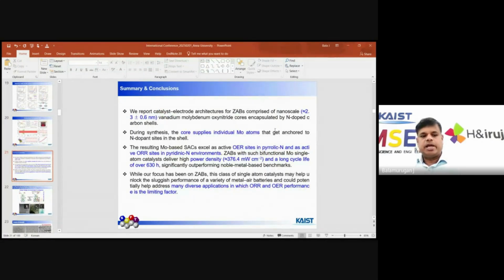So this is the summary, because whatever I discussed is similar, the peak power density. I told you the peak power density is very important compared to the other conventional material. Another thing, the durability is also challenging, because the durability is 630 hours compared to the conventional catalyst like a commercial catalyst. From the studies, we conclude that our developed catalyst for both OER and ORR has better performance compared to the other commercial catalysts as well as other counterparts.